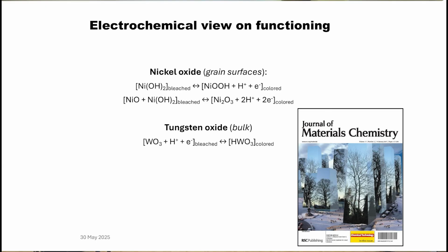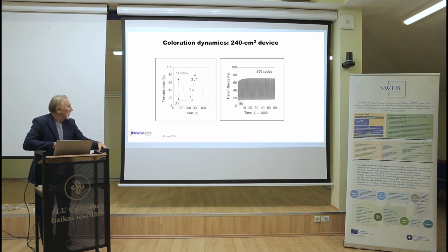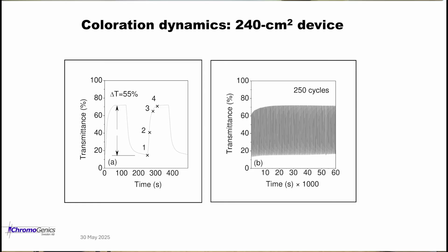About the physics, you can see this result, and maybe more detail in a review in the Journal of Materials Chemistry and so on, on how the reaction comes about. This reaction is obviously reversible, but there must be a problem of degradation and so on. Also, there is some data from Chromogenic that we have from the internet. The contrast is very good. You see transparency up to 70%, coloration up to 55%, and in the black state it is about 15. So it is a big contrast, and a very good product that the Chromogenic company offers in the world.